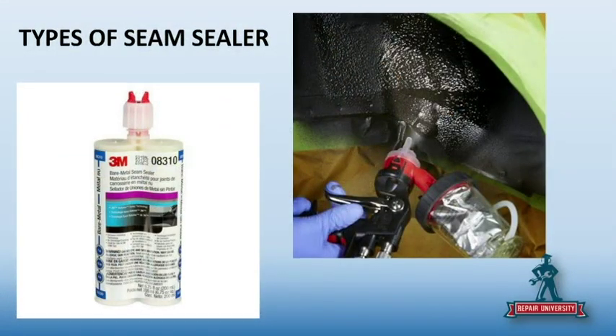And then you've got your bare metal and then sprayables that are available. Right, sprayable seam sealers as well. Just make sure if it's a sprayable seam sealer that it can go direct to metal if that's what you're doing. Right. And by the way, again, it all depends on the coating thickness and whether you have thorough coverage. So it may require more than one coat to get adequate coverage. Right. If you look at a sprayed seam sealer, you can see little spots of bare metal in between in a lot of cases. So it may need to be primed. I would personally prime under it. Well, say it's the suspenders and belt thing. Correct.